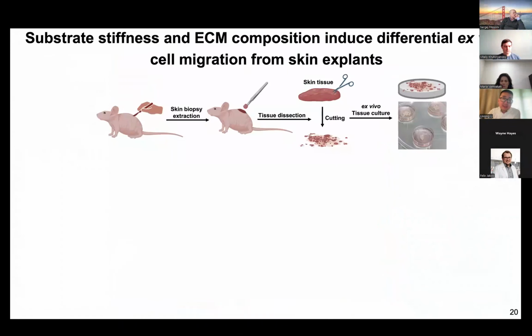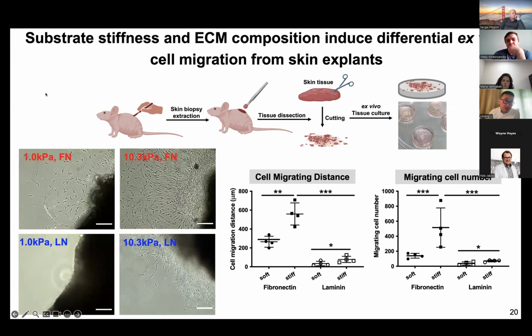So we are closing the studies using ex vivo studies, because we're trying to generate substrates to culture cells that have not been cultured on tissue culture plastic before. So we did these ex vivo studies in which we isolate the tissues from the skin, and then we put these tissues on the substrates we make. Interestingly, we chose two different models using different stiffness and different ECM proteins, and again we see that on the fibronectin coated surfaces you have directly stiffness modulated cell migration.